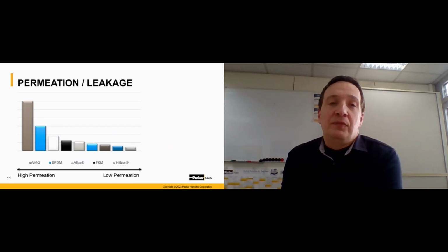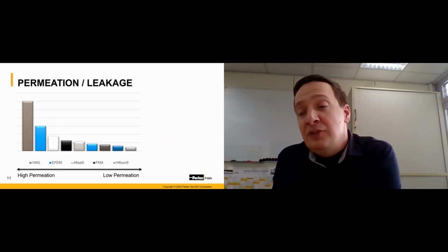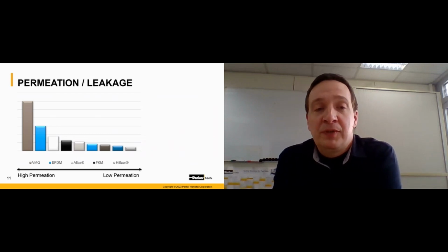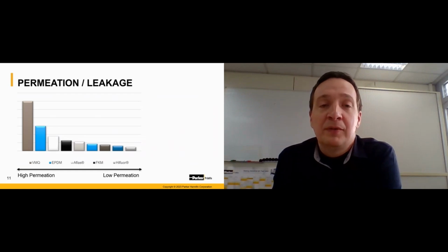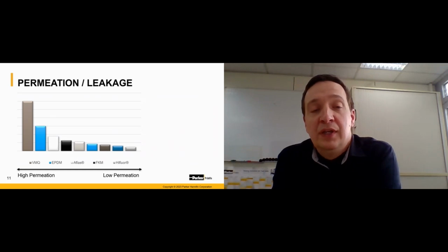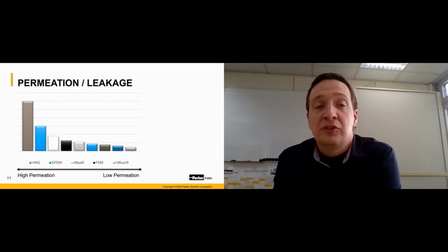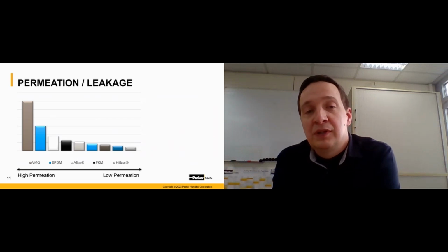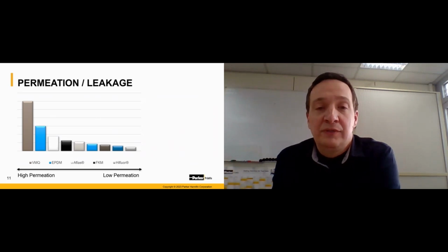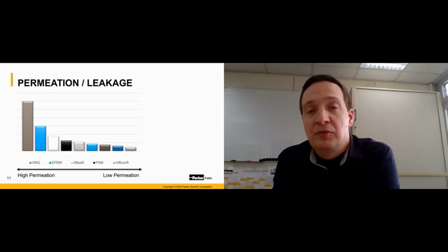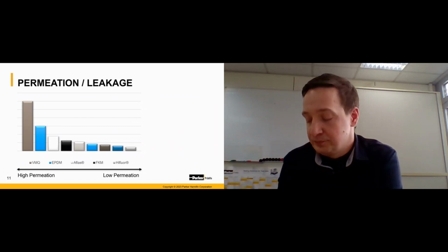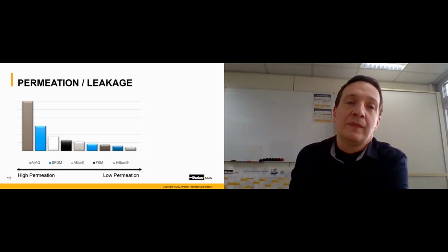And for permeation, the behavior of the material is different. Depending on the material class, the materials are showing different permeation performance. As you can see here on the chart on the left side, the silicone material is one of the materials which is showing the worst permeation behavior. The FKM is something you can find in the middle of this permeation chart. And if you look for the compound with the best permeation behavior, then you have to go to the right side, which is butyl rubber.